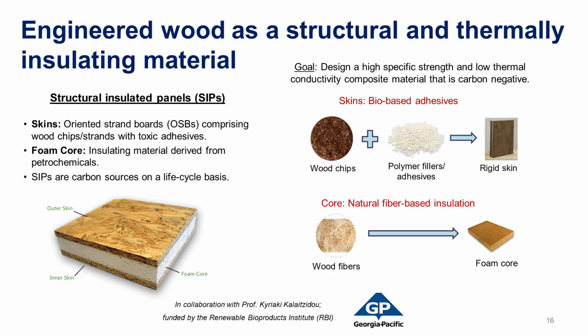And so the way we can do that is with this building component referred to as a structural insulated panel, or SIP. So the SIP is a sandwich structure. You have two wood panels referred to as oriented strand boards. You can make these with just wood chips. And typically, if you use waste wood, that improves everything on a life cycle basis. And in between these wood boards, we sandwich a foam core. This is usually styrofoam, which again is petrochemically derived. And this SIP structure can hold weight, meaning that it's a structural material, but it can also act as your thermal insulation. So it serves two purposes for the building itself.